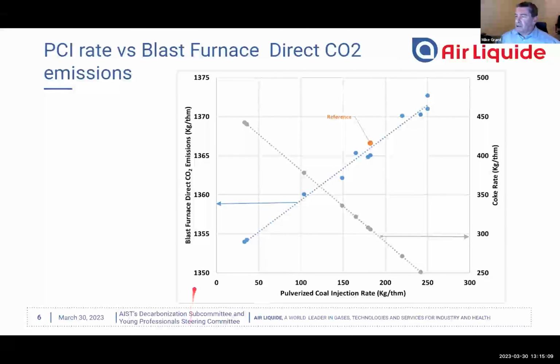Now let's look at the CO2 emissions. Well, if we're just looking at the direct emissions of the blast furnace, we see that they start to increase as we increase our coal injection. And why is that? Because the coke replacement ratio is less than 1. So we have to inject more than 1 kilogram of coal to replace 1 kilogram of coke. And this increases the overall direct CO2 emissions of the blast furnace.